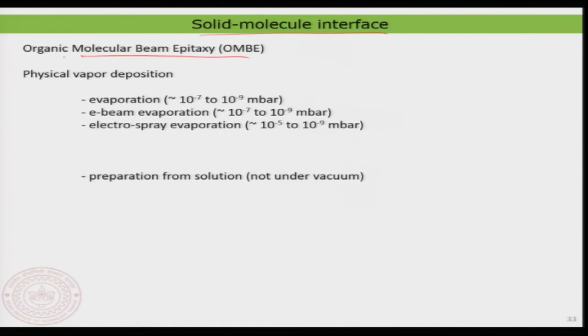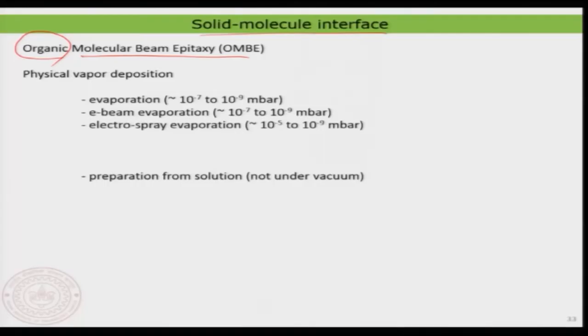But since here we are using organic molecules, we are actually doing the so-called organic molecular beam epitaxy. The organic represents that you are now going to deposit molecules onto the surface, and that is why it is called organic molecular beam epitaxy, or generally known as OMBE, and in the other case, you remember, this was typically the so-called molecular beam epitaxy. So the general preparation methodology for molecular beam epitaxy or organic molecular beam epitaxy is just physical vapor deposition, and the physical vapor deposition is done like in the previous case using either evaporation or e-beam evaporation, or even sometimes something known as electrospray evaporation. That's the one which is different compared to the previous case.